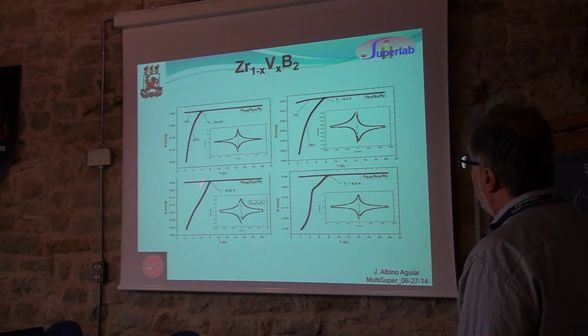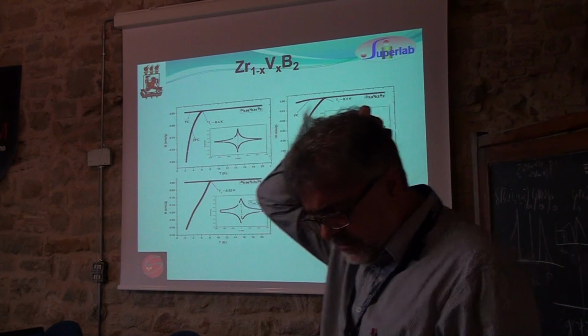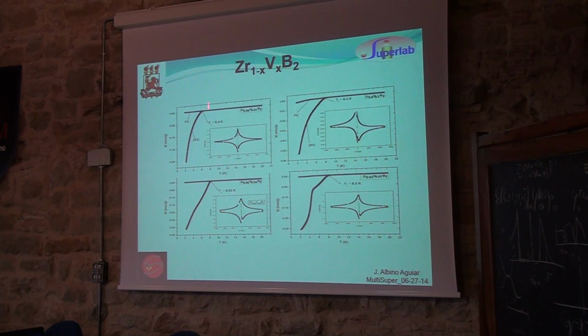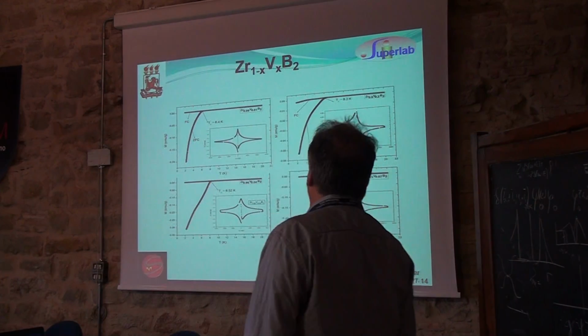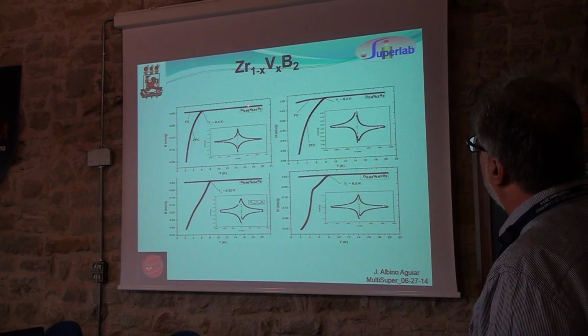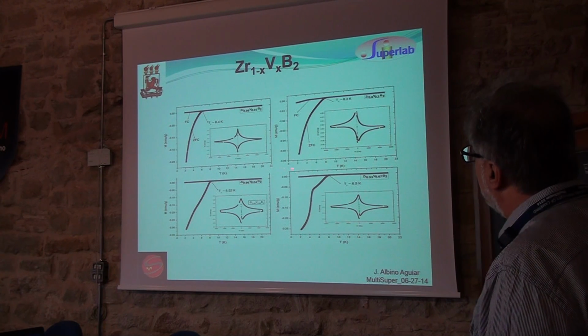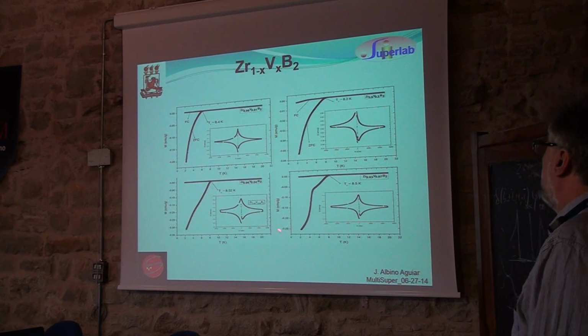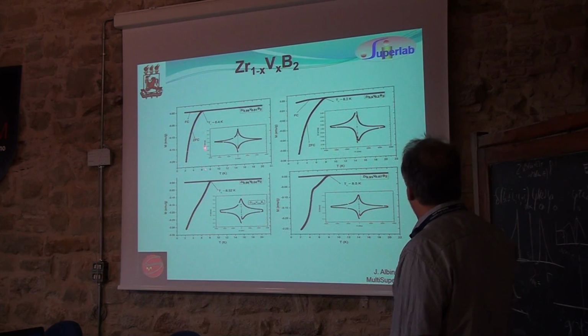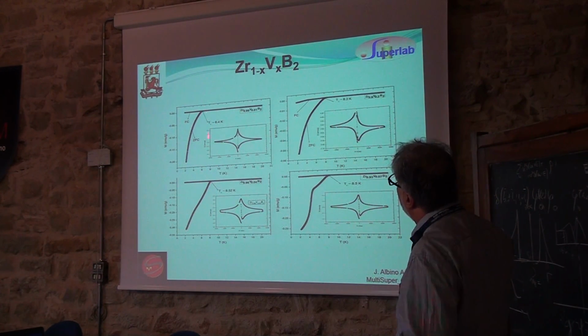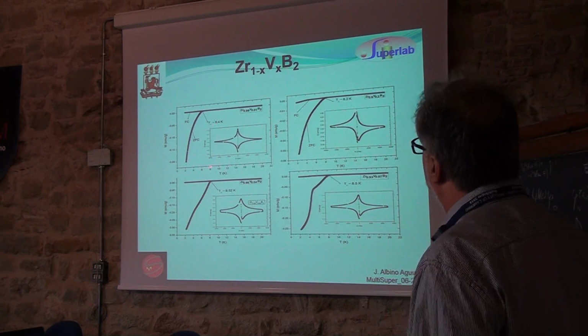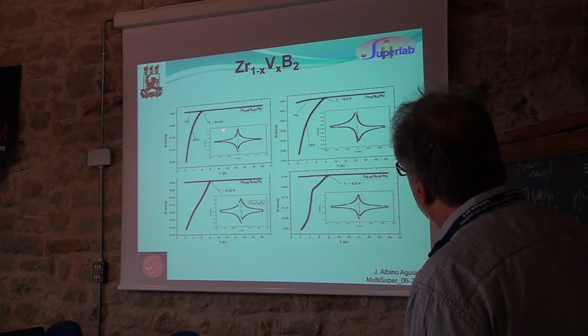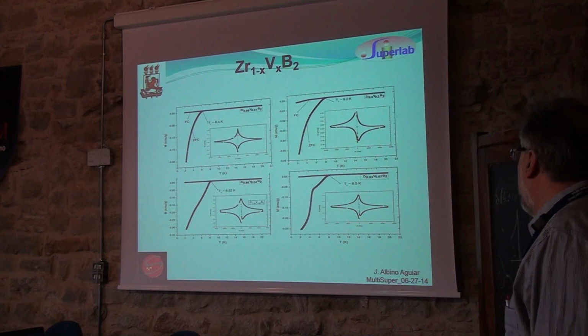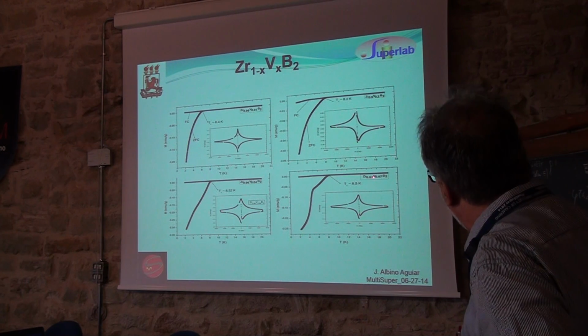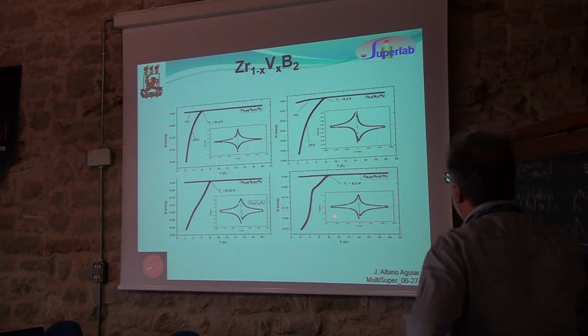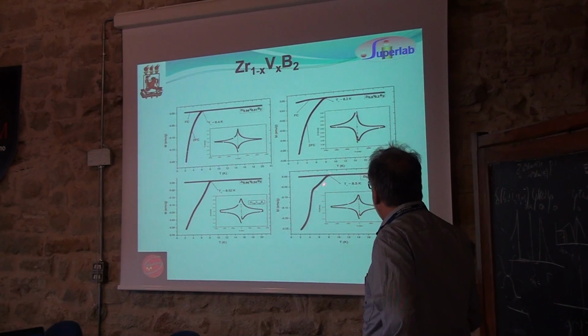So these are the temperature dependence of the magnetization in FC, ZFC scheme. And you see that all samples, 1%, 2%, 3%, 4% vanadium dopant, we have a clear superconducting transition. We have the irreversibility line. In the inset we show M versus H. And for example, for this sample here, we have a double transition. Maybe there is a mixed phase.